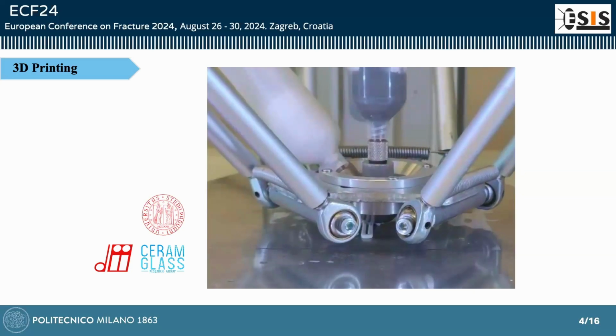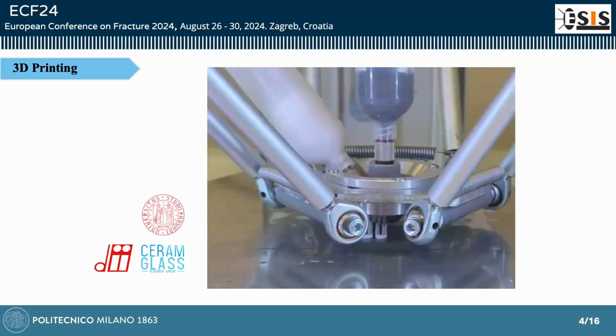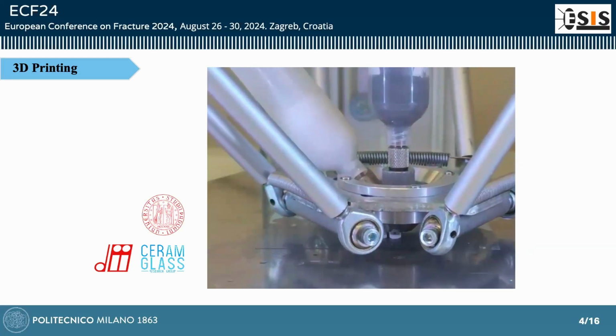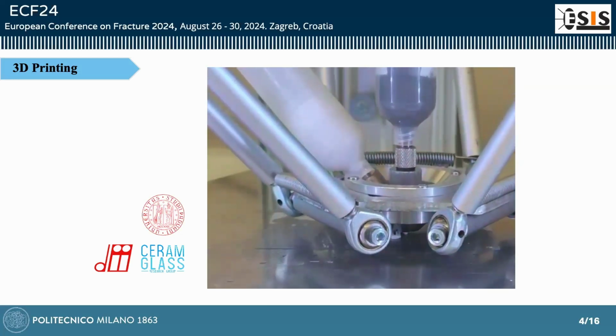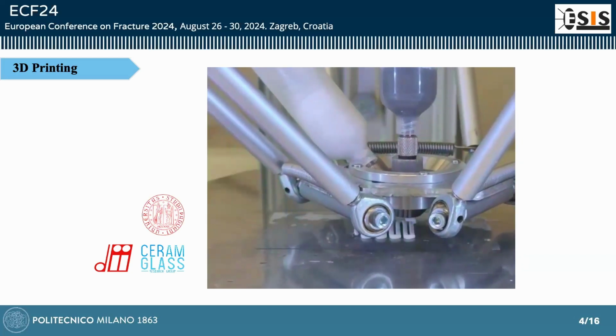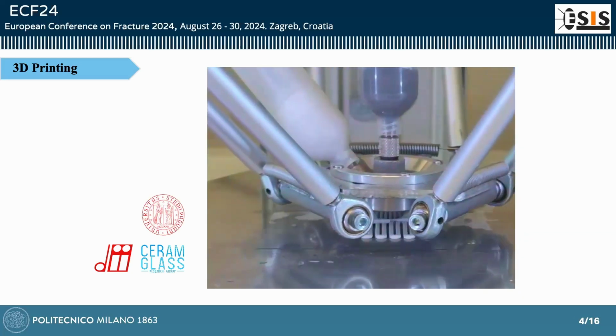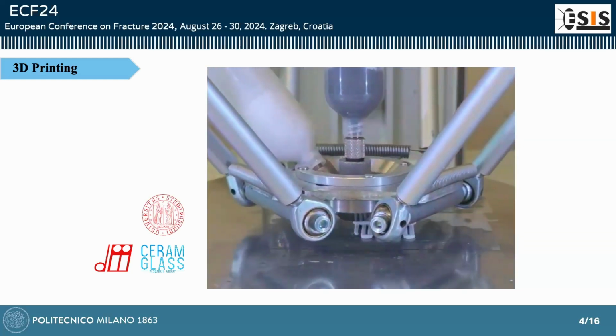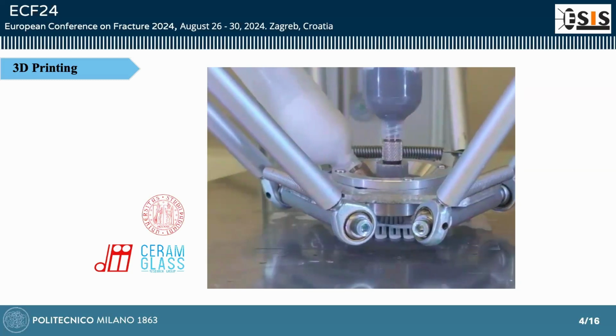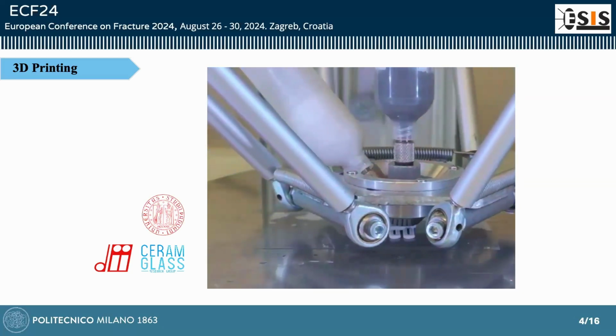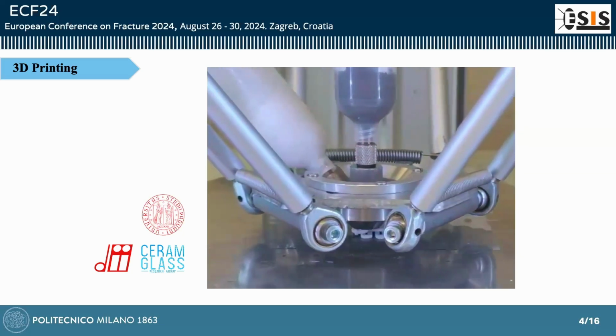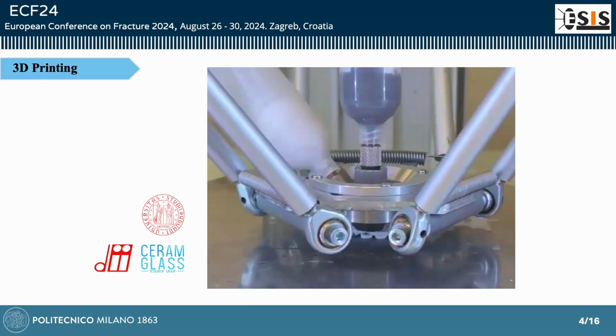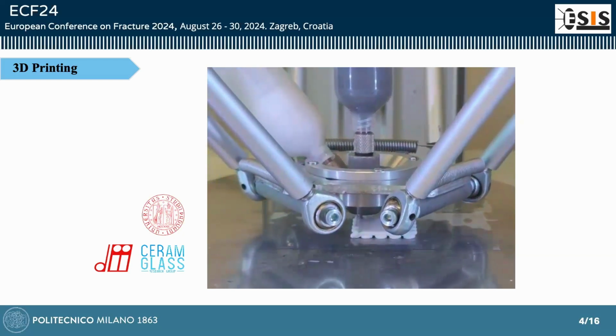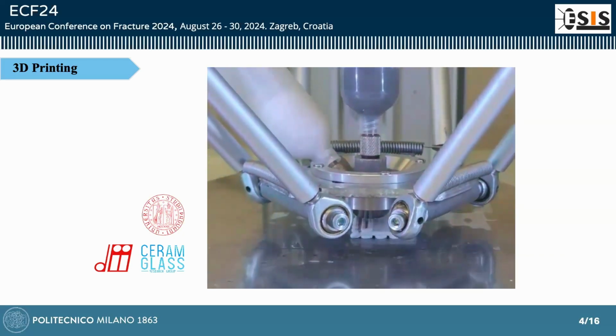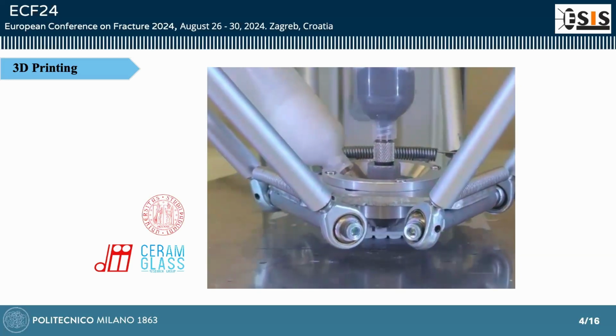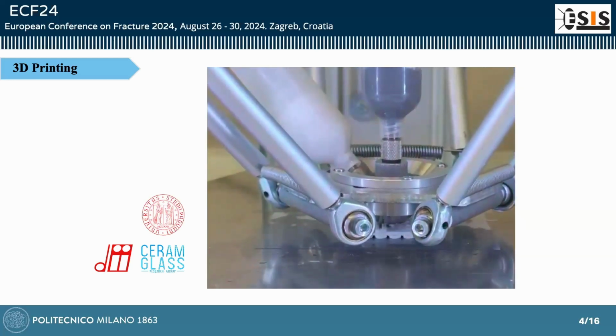Our specimens are going to be produced at University of Padova in Italy. The 3D printing technology that is going to be used is coaxial nozzles, and the ink is based on metal and ceramic powders, which are embedded in visco-epoxy resin that is going to evaporate during the sintering process. At the end of the process, we see that the microstructure of the final material is very porous. The porosity is more than 40%. So it makes us evaluate the material properties of these microstructures.